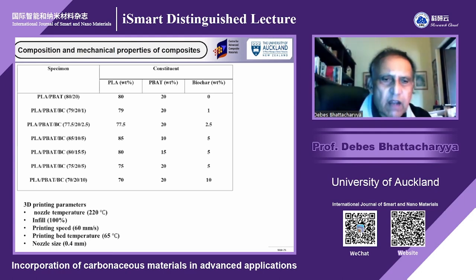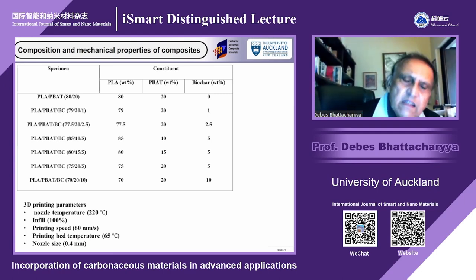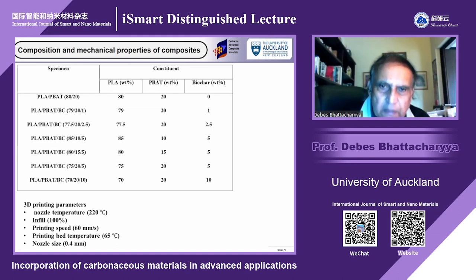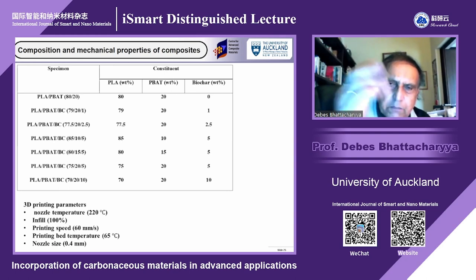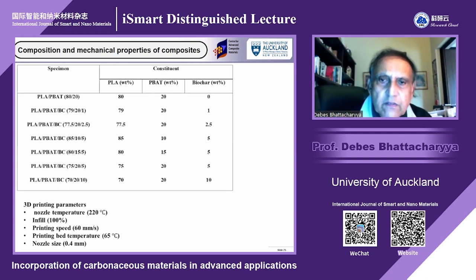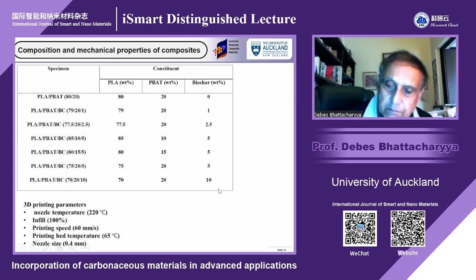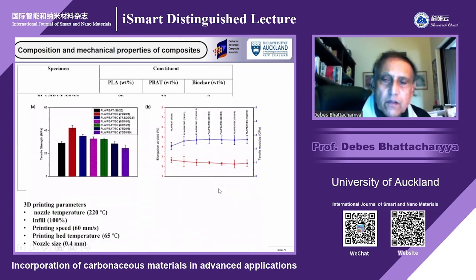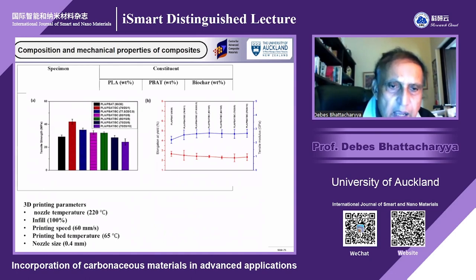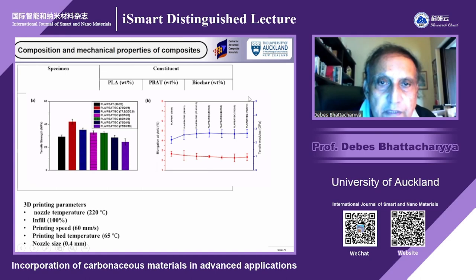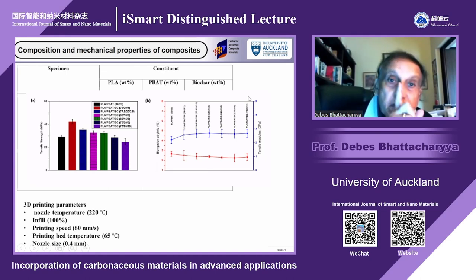We go on trying, and to an extent it is a bit trial and error, but we try to create an overall picture. We try to keep the PBAT percentage as constant as possible. We did not want to go too high on biochar because that creates problems in the actual printing process. So you can see that the highest one is the red, which is 79, 20, and 1% biochar,